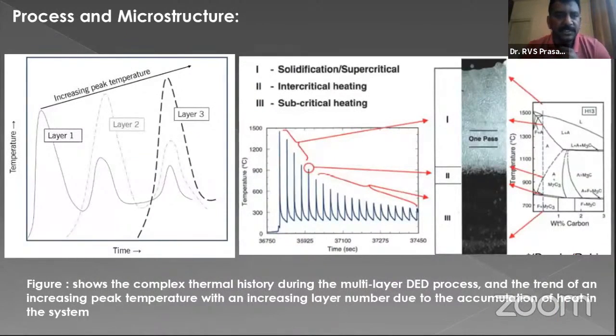When it comes to the process and microstructure of direct energy deposition, it's very interesting with respect to the metallurgy involved. If you consider this diagram of temperature versus time, you have different layers. For layer one, initially the peak temperature is very high. However, it comes down as the other layers build up. Similarly, once the second layer comes up, the temperature will be different, and once the third layer comes, the peak temperature increases as you deposit more layers.